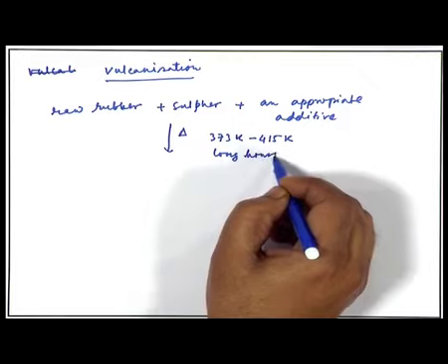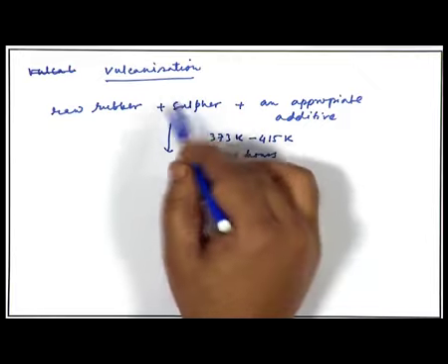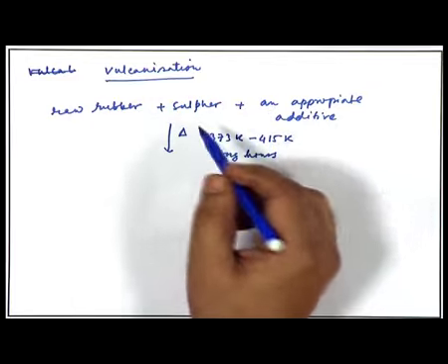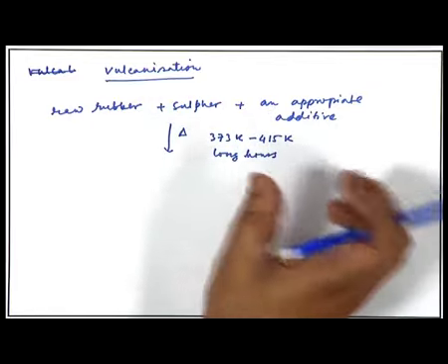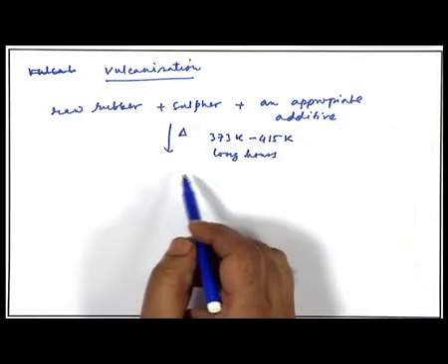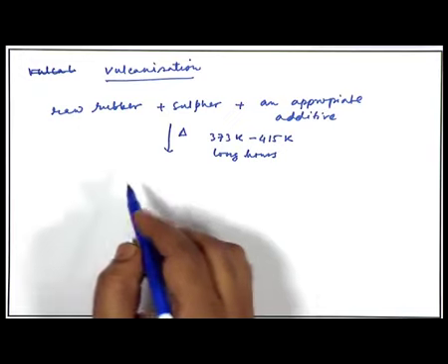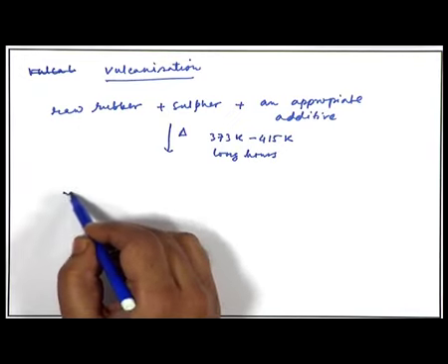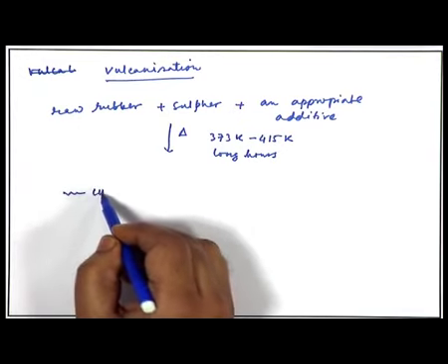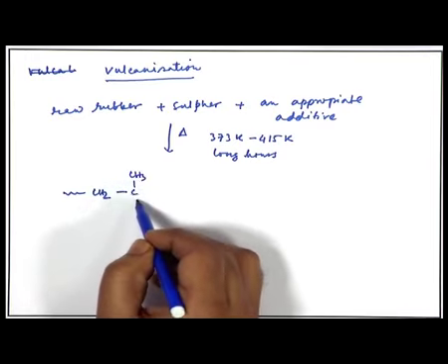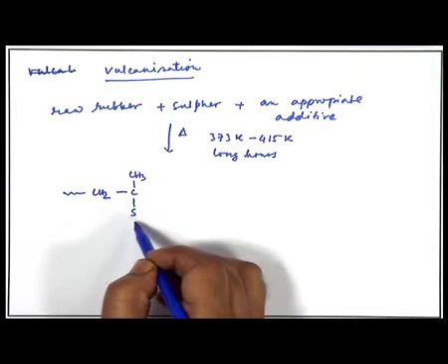It takes time, and the amount of sulfur is small, probably between 1 to 5% in the general case, but it could be even smaller or higher if required, and you get different cross linking products, and we are just writing a few structures.